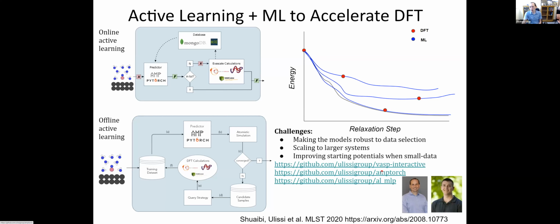The calculations that we do on the catalysis side are so expensive that we want to play all the games that we can to reduce the number of DFT calculations to the very, very bare minimum. To give you an idea of what's currently possible, it seems to be relatively easy to reduce the number of calls by about a factor of 2, which is good but not incredible. And I think there's stuff coming that should make it even better than that, especially when you're sharing calculations among multiple relaxations. Okay, this is sort of a small data mindset. I'm just running a single calculation. Can I make this thing run faster than I would be able to otherwise?